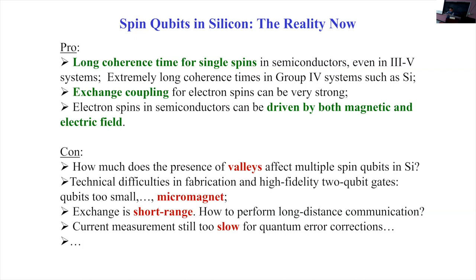There's no clear indication yet. And when you go to larger samples, I think several experimental groups are pushing to like 6 qubits and things like that. But still, no concrete evidence to show those same high fidelity gates yet. Okay, so in silicon, there are still multiple issues that we face, starting from the conduction band structure that is somewhat more complicated than gallium arsenide, which I will discuss later, the so-called valley physics. And also, I would say from the long-term perspective, the difficulty in implementing all the micromagnets that allow us to have that magnetic field gradient and the artificial spin orbit interaction.